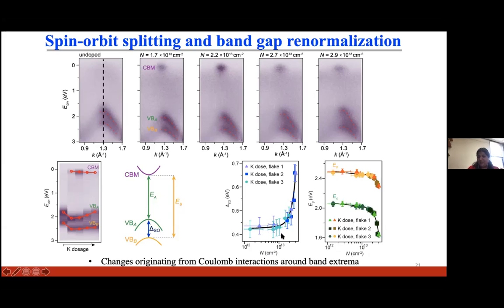But as we dope more and go higher than 10 to the power 13 dosage, the splitting is actually increasing. Similarly, if you look at the separation between the conduction band and these two branches of the valence band, we observe that at higher dosages, these separations start to decrease. So what's happening here is that the spin orbit splitting enhancement is happening when we are putting a lot of electrons, which means that the origin is the many-body interactions in the system.